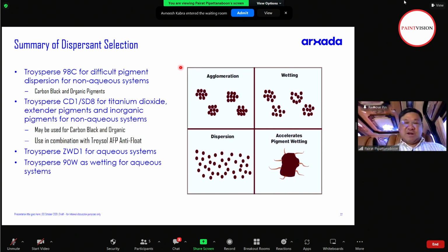So, a summary of the dispersants that we have. When you have a solvent-based system, non-aqueous, including UV, you have 98C for the hard-to-disperse pigments, like carbon black with high surface area, for example, Raven 5000 Ultra, and organic pigments, color blue, color green, or violet. You use CD1 or SD8 in case you need to disperse TiO2 or inorganic pigment, and also the grind for alkyd paint. SD8 is a green chemistry version of CD1, which is derived from some raw material from palm oils.